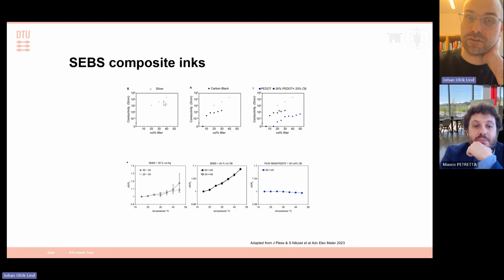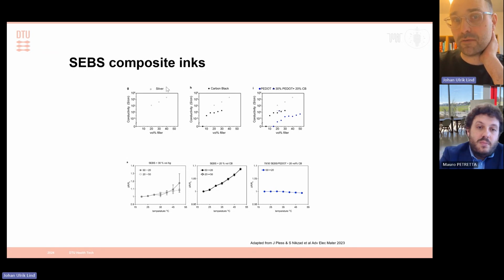So you can of course work with the compatibility of the silver, but we found that, for instance, silver composites with thermoplastic polyurethane were more stretchable than SEBS composites were. And the same was actually true for PEDOT. So we actually anticipated the PEDOT composites to be the most stretchable. We found two things: we needed to add more to get a decent conductivity, but also they actually compromise the stretchability the earliest.